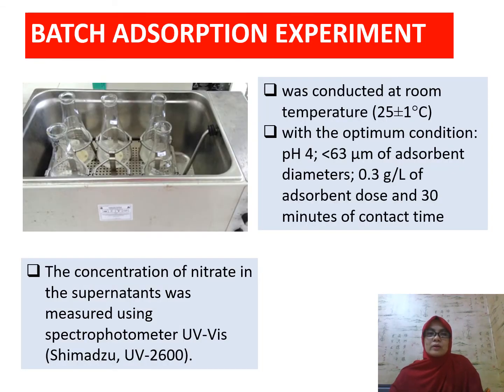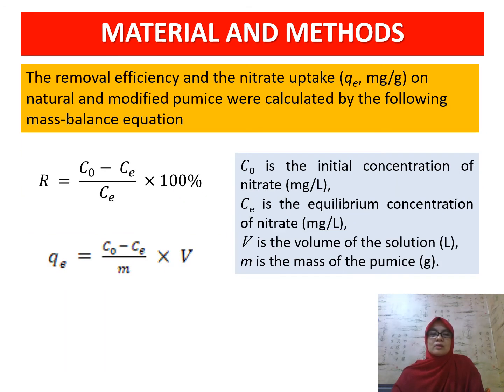After that, we conducted batch adsorption experiment at room temperature with the optimum condition: pH 4, less than 63 micrometer of adsorbent diameter, 0.3 gram per liter for adsorbent dose, and 30 minutes for contact time. The concentration of nitrate in the supernatant was measured by using UV-Vis spectrophotometer. This is the equation that we use to calculate the removal efficiency and the nitrate uptake on the natural and modified pumice.